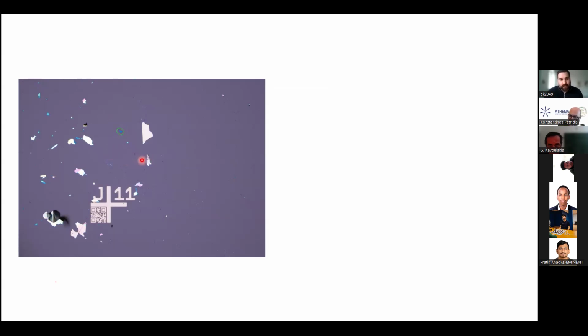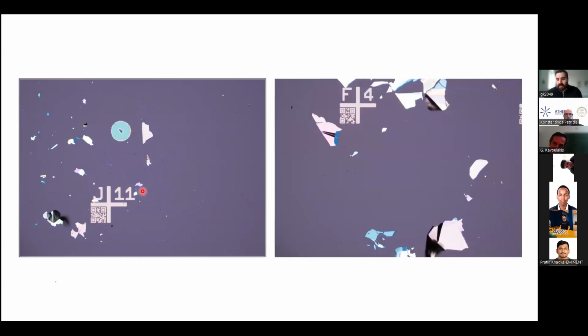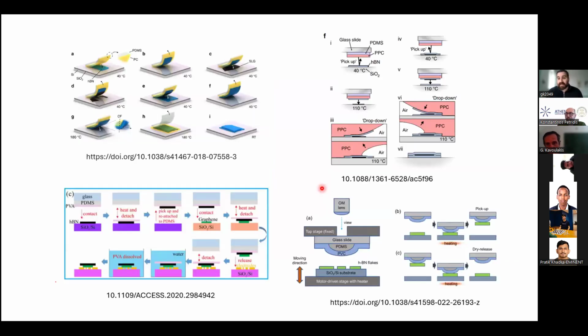It doesn't only do that, but it also gives me details about the surrounding area. This is very important because if someone wants to go and pick this up, it needs to be free. It needs not to have debris around or other flakes. Otherwise, the whole process will be hindered. Now, here, for example, the code will recognize that we have the same thickness of flake, but it's attached to the bulk. So it's of no use. We cannot pick it up. So this code is really useful to help us identify, very fast, exactly where the flake of our heterostructure is, and go and pick it up later with pick and place techniques.